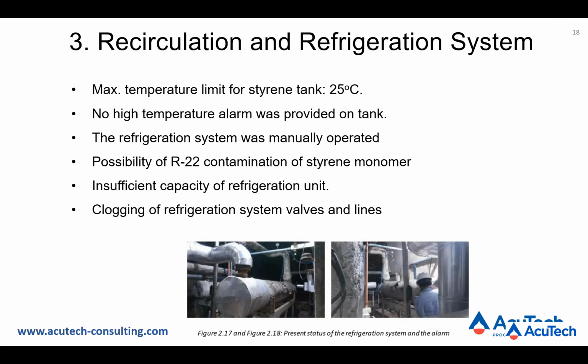It was also put forward that possibly the styrene contamination could have happened due to leaks in the refrigerant system because the mechanical integrity of the cooler in the refrigerant system probably was not ensured. Possibly there were chokings inside the refrigerant system valves and lines which might have clogged during the shutdown period, and the contents could not have been cooled as the pump motor had tripped due to the viscous polymer present.